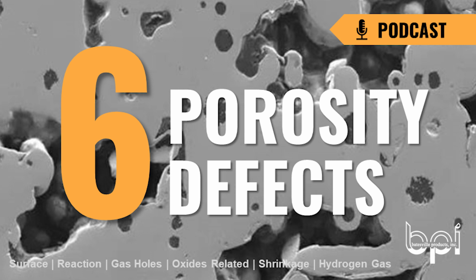These slides here happen to be shrinkage cavity. You've actually failed to get metal into that portion of the part, and it's actually isolated a cavity. It commonly happens in a couple of places. One is the last place to solidify. It'll happen a lot towards the gate. Also, it happens between thick and thin walls of the casting. If your risers are working the way they should be, you shouldn't get too much shrink.